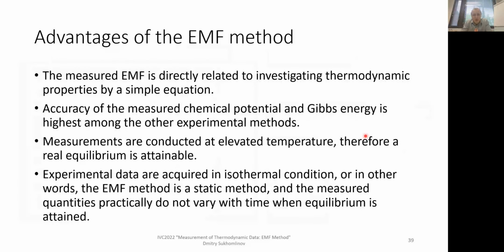So the advantages are that EMF is measured directly and calculations are pretty straightforward. With the Nernst equation and with some conditions regarding the standard state of the substances, we can convert measured EMF and temperature into the Gibbs energy of our reaction. It's pretty accurate because it is direct. We directly measure activity, we directly measure Gibbs energy.